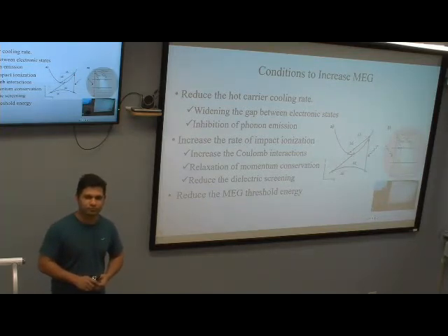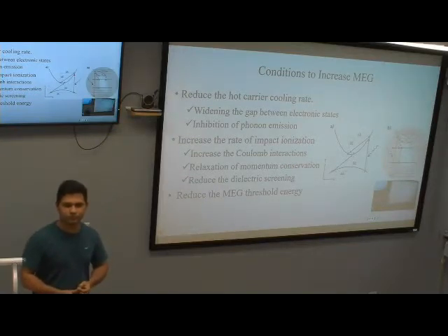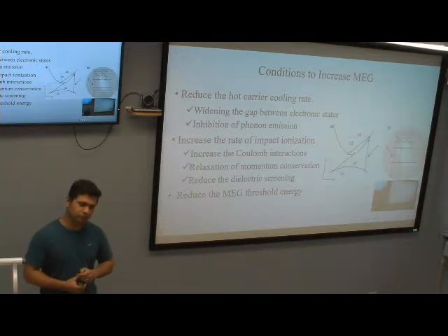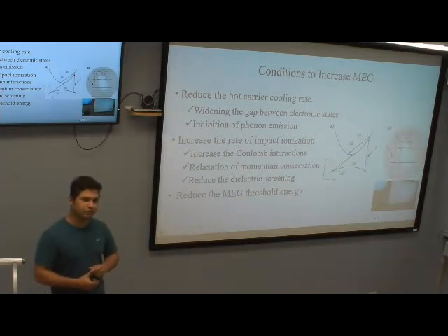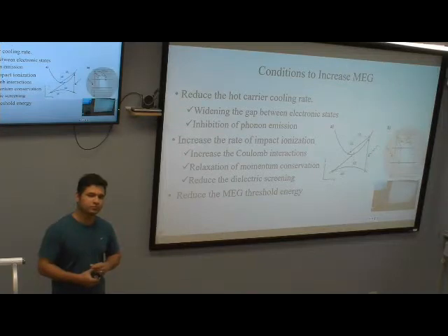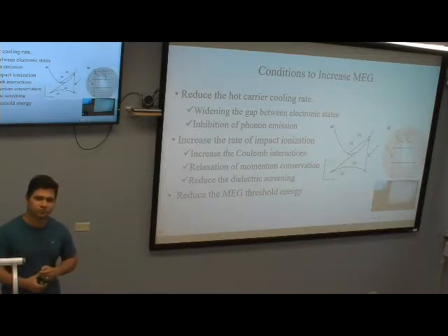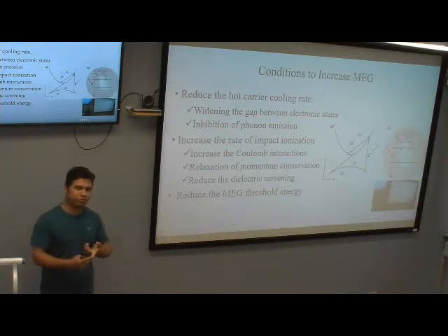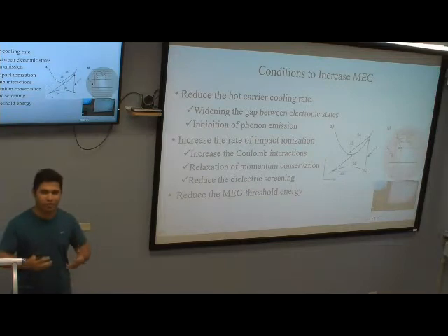So as you go from 3D to 2D, 1D, and 0D as quantum dots, you reduce the momentum conservation degrees of freedom. And going to 0D, it's not really taken into account anymore. So momentum conservation is a condition, but now we are looking at the probability of happening or avoiding these conditions in what type of materials.